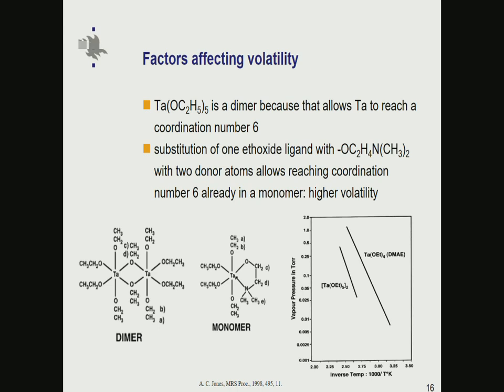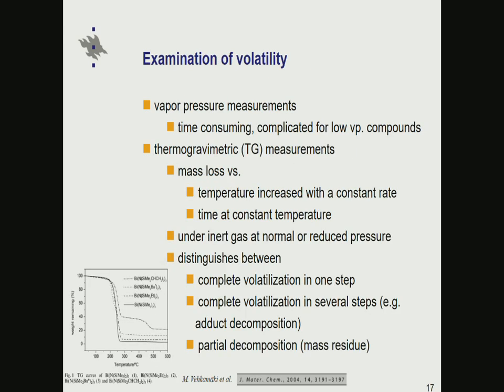Now, by simply changing one of the ethoxide ligands to an amino ethoxide ligand, we have in this ligand 2 donor atoms which can bond to the tantalum: oxygen, as in the other ligands, but also nitrogen. As a result, the requirement of coordination number 6 becomes fulfilled already in a monomeric precursor. The molecular weight is lower, and that translates to a higher vapor pressure for this donor functionalized alkoxide as compared to the parent alkoxide itself. So these are very simple tricks to increase the volatility.